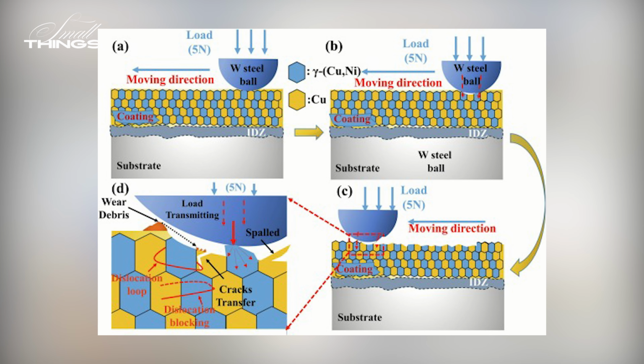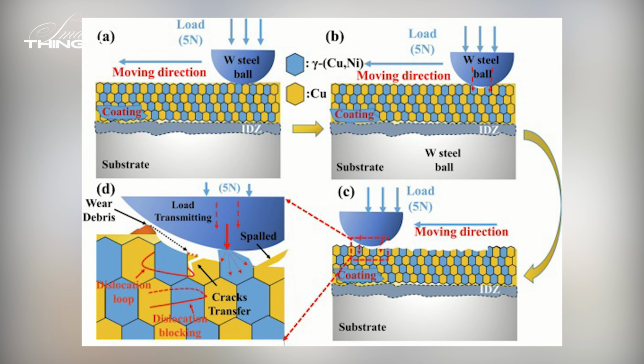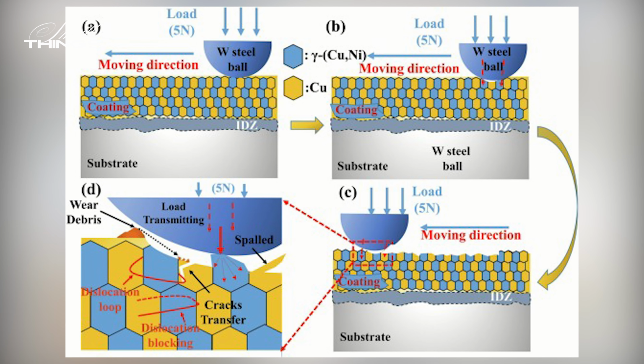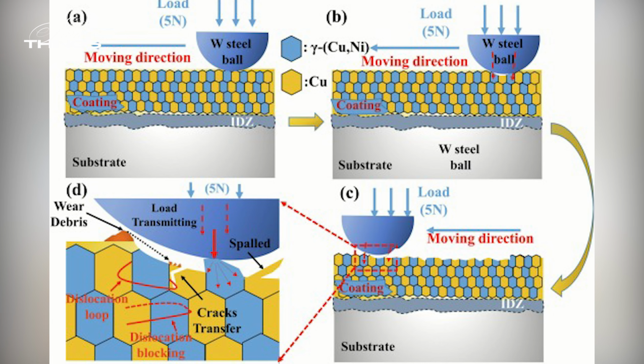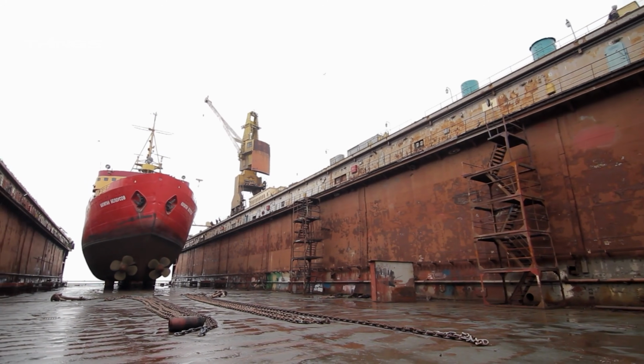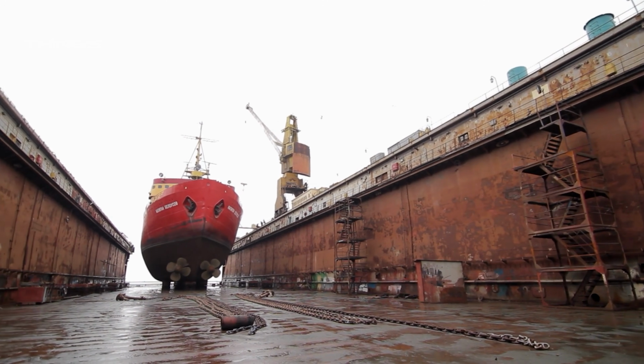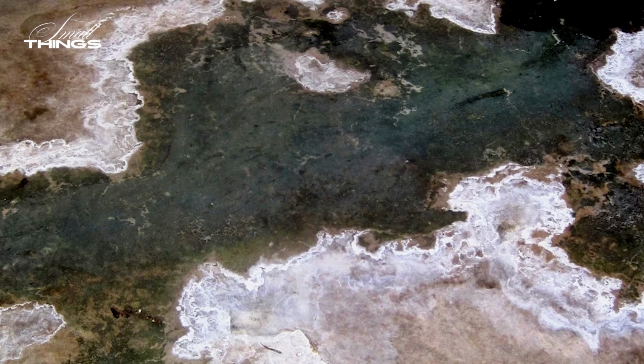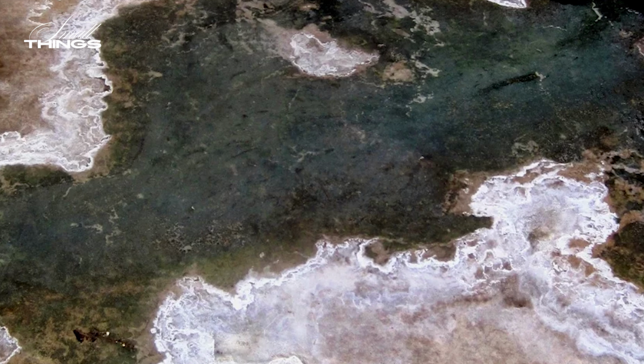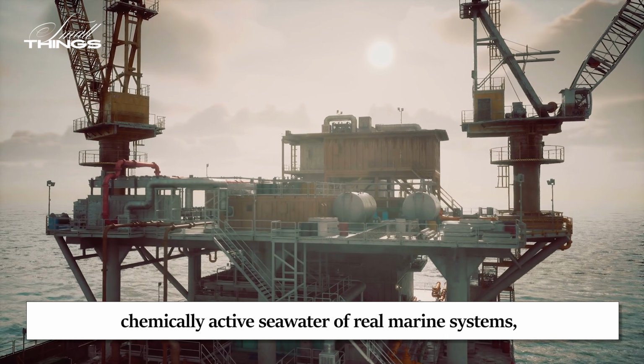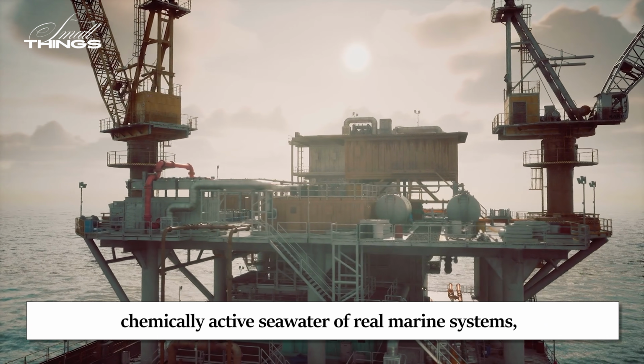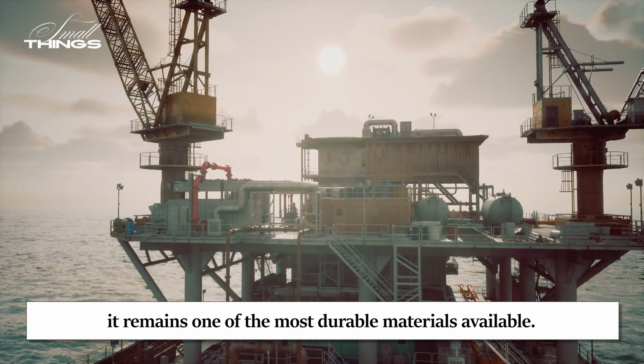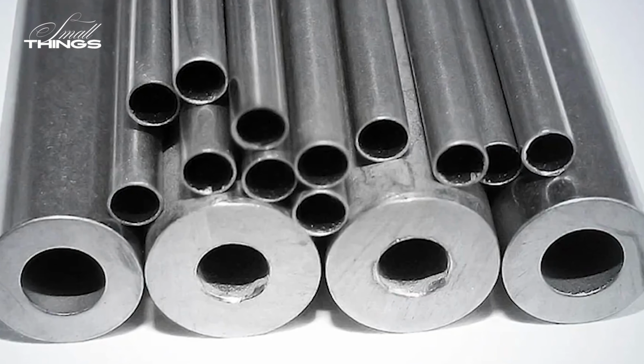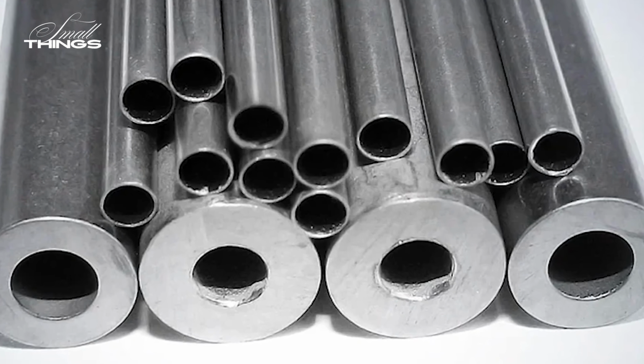Monel works differently. Its nickel-copper structure forms a surface that is resistant to chloride attack without needing to maintain a delicate passive film. It performs particularly well in flowing seawater, where its corrosion rate drops to almost nothing. The one condition where it is less effective is stagnant saltwater, where biological fouling can change the local chemistry near the surface. But in the moving, pressurized, chemically active seawater of real marine systems, it remains one of the most durable materials available. And there is one more thing seawater does that most people do not think about.